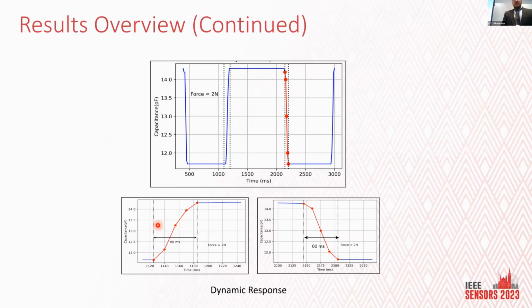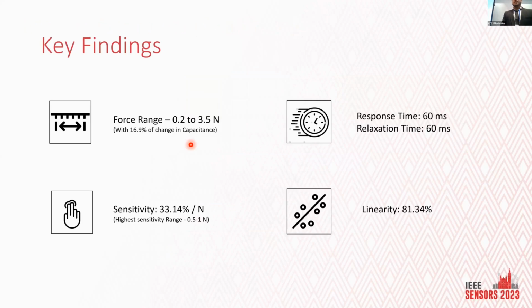And this is about the dynamic response. We can apply a step input. This is basically a no load condition, and if you apply load, the capacitance gets reduced. If you zoom into this portion, you will get the time response, the delay in achieving the final state, which I found to be 60 milliseconds in both loading and unloading. So these are the key findings. The force range we have found is 0.2 to 3.5 Newton, and the highest sensitivity is 33.14% per Newton. When you fit the model with a linear regression, we get a linearity of 81.34%, and these are the response times which I have got.